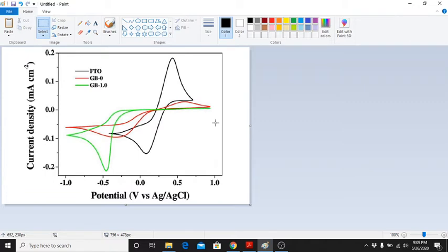Oxidation releases an electron. So what happens here, you can see with FTO, we use cyclic voltammetry. There is a larger anodic peak here, oxidation occurs, because oxidation releases an electron. So the electron of the FTO will recombine with the redox electrolyte. By having a compact layer, the oxidation process is reduced. You can see less electron will recombine with the redox electrolyte, which leads to a low recombination effect. If you have a very good compact layer, you can totally reduce the recombination effect by having no electron released at all, no oxidation process occurring at all. So that's why we focus on the oxidation part.